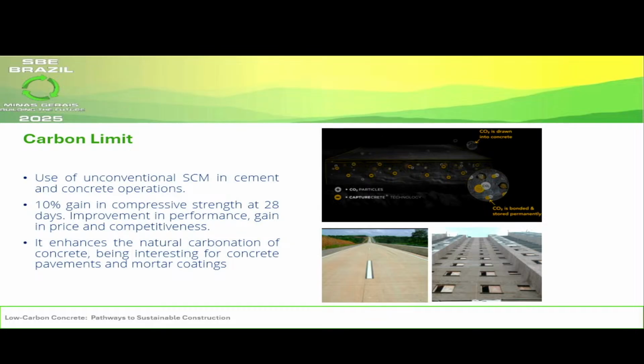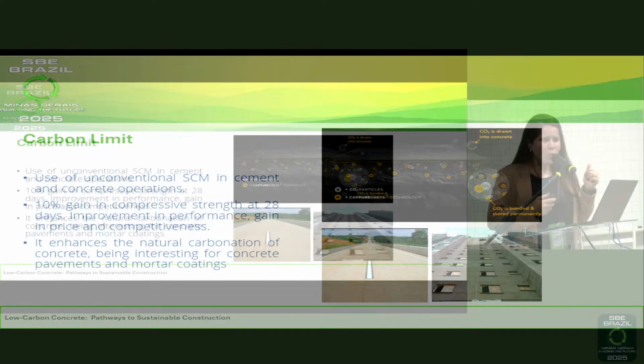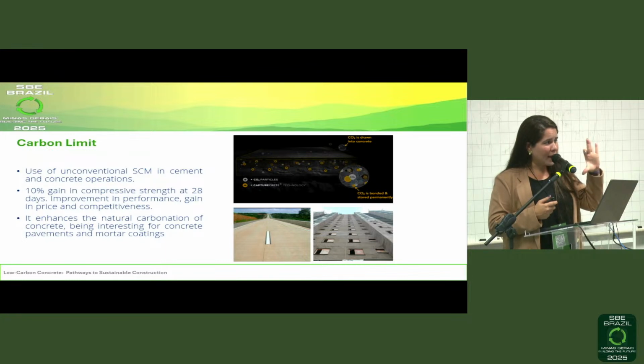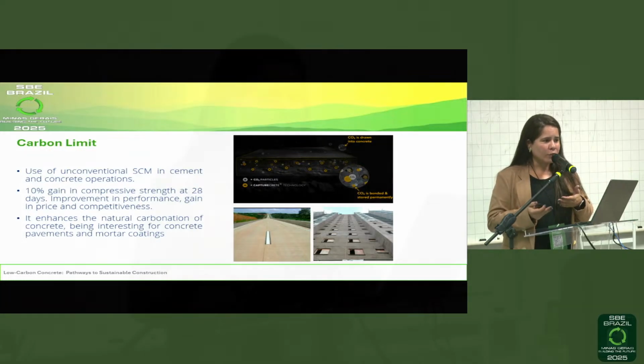In the case of Carbon Limits, this increase in carbonation for the concrete might not always be good. If we increase the depth of carbonation, we could start corroding the reinforcement. But if we are working on pavement, which has no reinforcement, we can work with an addition like Carbon Limits in pavement, where we don't have this problem with carbonation.